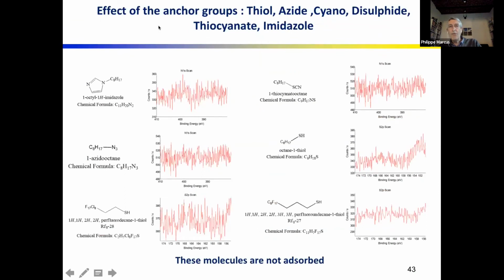We looked at the number of anchor groups now, looking at many different anchor groups. And what is collected here are all the anchor groups for which the molecules were not found adsorbed. So what we did essentially for all these molecules, we looked either at the nitrogen 1s signal in these different molecules, or we looked at the sulfur 2p signals for thiol molecules. And you see that in all these cases, you can see only noise, which means that none of these molecules is adsorbed at the surface. So obviously, you don't expect that they will be good inhibitors.